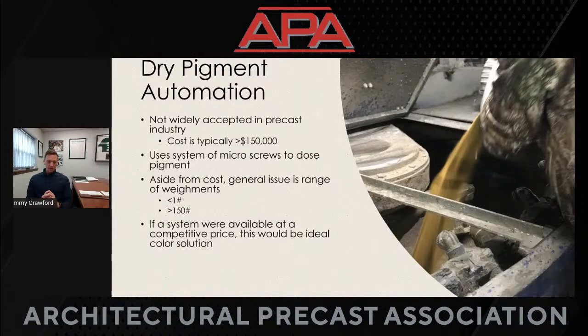Dry pigment automation. As I've alluded to, it's not widely used in the precast industry. The cost is typically in the $150,000 plus range. The systems that I have seen use micro screws to dose the pigment, so they're turning and dropping little dustings of the pigment to get those small addition rates. Aside from the cost, the general issue is the range of weighments, similar to the granular side. It's not uncommon, especially in the precast industry, that you might weigh up less than 1 pound of material in one mix and greater than 150 pounds in another mix.